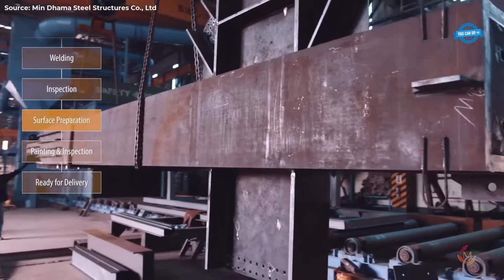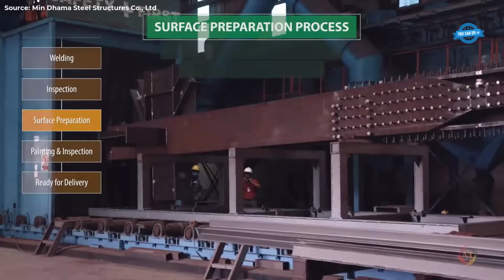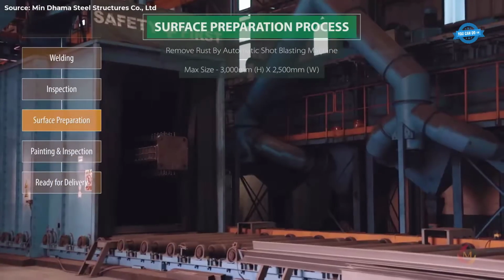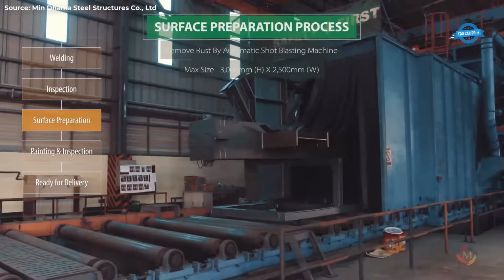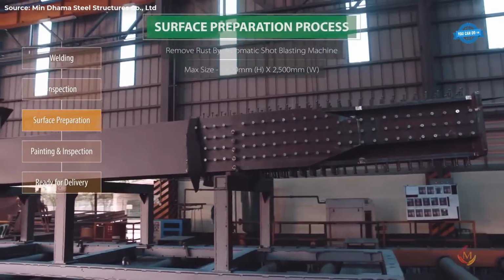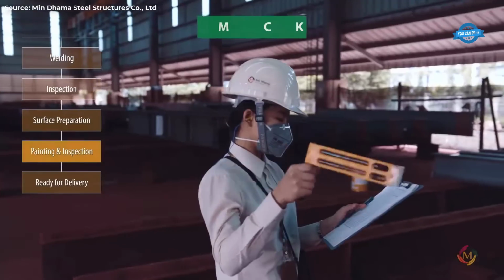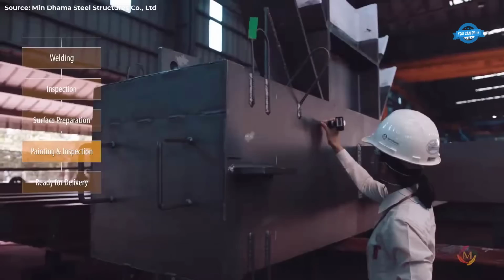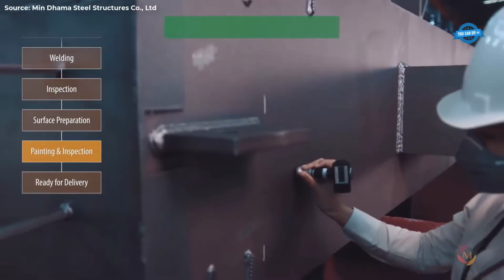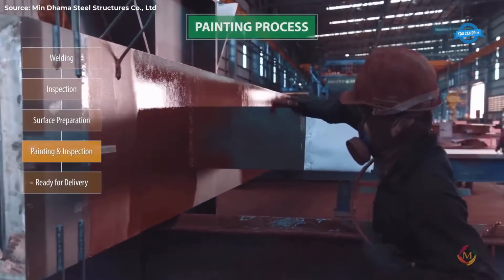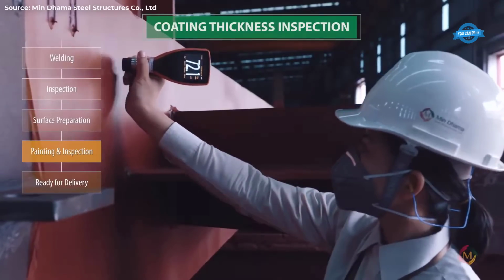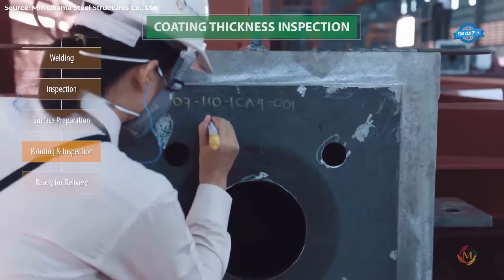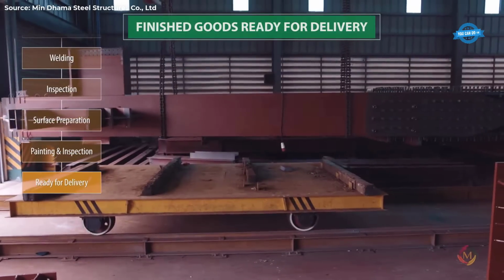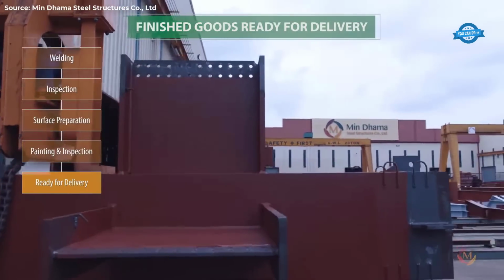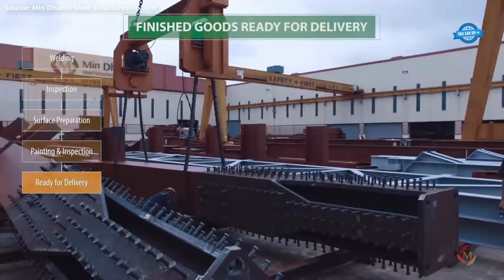Surface preparation involves the removal of rust using an automatic shot blasting machine, preparing the surface for painting. Surface roughness inspection ensures proper paint adhesion and protection, after which the box column undergoes the painting process for corrosion protection and aesthetic enhancement. Coating thickness inspection is conducted to verify compliance with specifications. Upon successful completion of all quality checks, the finished box column is prepared for delivery to the customer, ensuring that it meets the highest standards of quality and reliability.